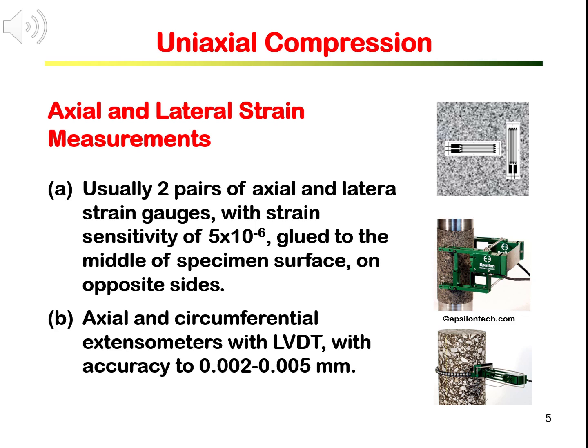Another common device for deformation measurement is LVDT. The middle right photo shows the axial displacement extensometer. It measures the axial displacements between the pair of legs, which are on sides of the specimen. The lower right photo is the circumferential displacement extensometer. It is a chain device around the specimen circumference at the middle height and it measures the whole circumferential displacement. Both devices use LVDTs for actual measurements with accuracy in the order of micrometers.